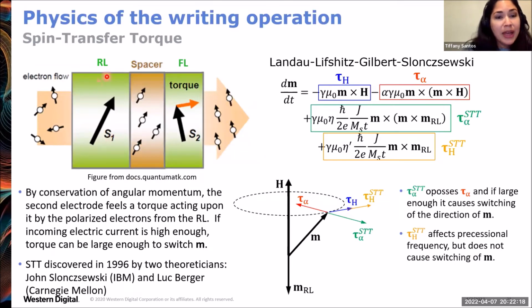So I'll describe that. This is your 3 layers of the tunnel junction and a current passing perpendicularly through the layers. So by conservation of angular momentum, the free layer feels a torque acting upon it by the polarized spins coming from the reference layer. And if that current is high enough, then the torque will be large enough to switch the magnetization.